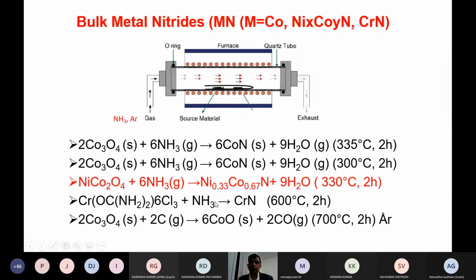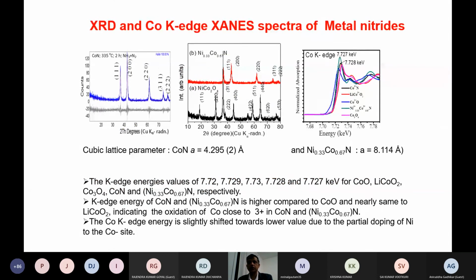Again, remember chromium nitride is very hard, and we try to prepare the sample at low temperature, but a minimum of 600 degrees is needed. And if you want to pass with, for example, carbon, we can get the respective oxide also in argon atmosphere. So that's how we can reduce Co3O4 to cobalt oxide in the 2+ state. And in this simple XRD, for example, NiCo2 oxide is converted into a simple cubic nitride. Okay. Similarly, cobalt nitride.